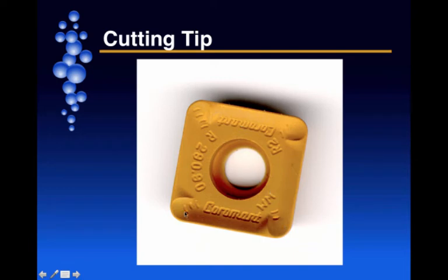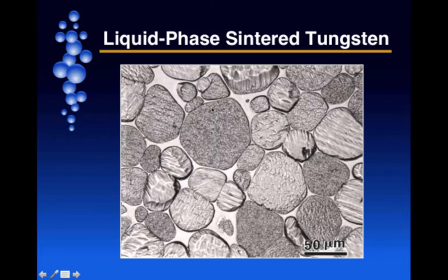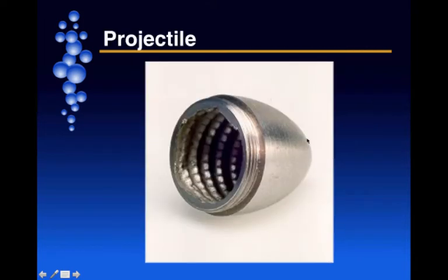Of course, this gold color that is obtained is, for instance, from a coating of titanium nitride to provide sufficient heat dissipation at the cutting surface. Another microstructure that's liquid phase sintered is this tungsten heavy alloy. So these are the tungsten regions, and this typically the iron nickel regions that are lighter phase. And so projectiles is one type of application for this.